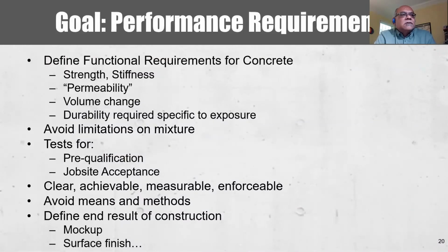When we try to evolve performance requirements for concrete, the designer, generally the structural engineer, has to evaluate the strength requirements. That's generally easy based on the loads. In some cases with high-rise structures, you have to look at stiffness, such as modulus of elasticity and possibly creep. For concrete exposed to conditions that impact durability, you have to look at some measure of permeability, most commonly the water cement ratio, but there are performance-based test methods that can evaluate that.